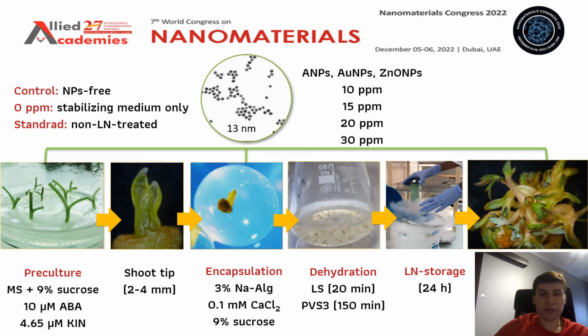The addition of nanoparticles, especially of gold nanoparticles and zinc oxide nanoparticles into the capsule was particularly effective because the explants that were treated in such a way increased their survival after cryogenic storage from 20 to even 30%, and that was really a big improvement.